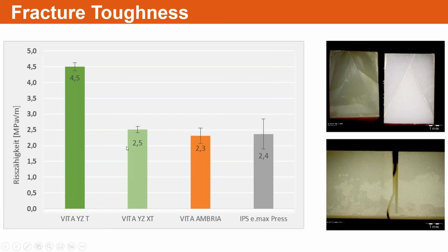So if you're interested, the Ambria is about 2.3. We're basically equivalent with the EMAX. I know it's 0.1 difference, but again, if you look at the deviation, the materials that we produce are a little bit more consistent. So of all the products, let's say you do 100 tests and try to find out what the fracture toughness is, the ones that have the highest measurement, 50% of them, this is the top, that's the 2.3.